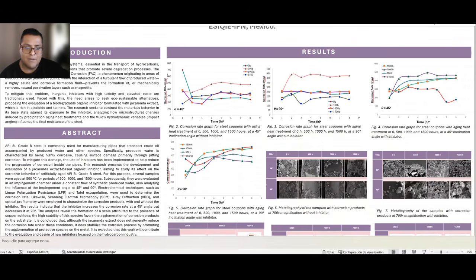As we know, API 5L Grade B carbon steel pipes are essential for transporting hydrocarbons. However, they frequently operate under critical conditions and suffer from a severe degradation process called flow-accelerated corrosion, or FAC. This phenomenon usually happens in areas where the flow changes direction, like elbows and joints. The turbulent and highly saline produced water removes the two natural protective passivation layers on the steel, such as magnetite.